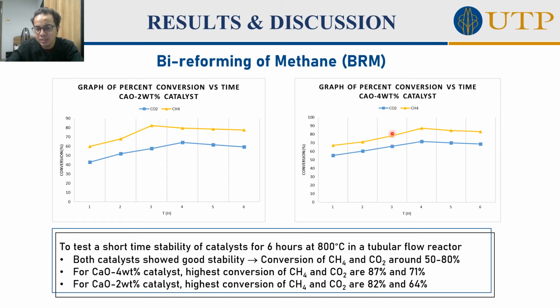So basically, this catalytic testing is to test a short time stability of catalyst for 6 hours at 800 degrees Celsius in a tubular flow reactor. So based on these two figures, we can conclude that both catalysts showed good stability, where the conversion of methane and carbon dioxide is around 50 to 80% for both catalysts.